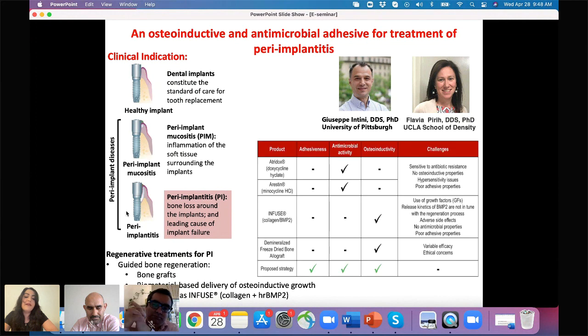So when we look at different treatment options, including Infuse, there are some limitations. Basically, Infuse can help bone regeneration, but it doesn't have any antimicrobial properties. Therefore, they have to use it in combination with different types of antibiotics. The treatments that have an antimicrobial effect for peri-implantitis treatment don't lead to bone regeneration. So our goal was to design a strategy or a biomaterial that has three properties together: adhesion, antimicrobial